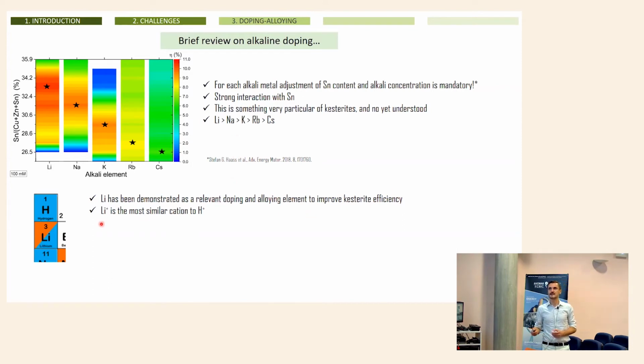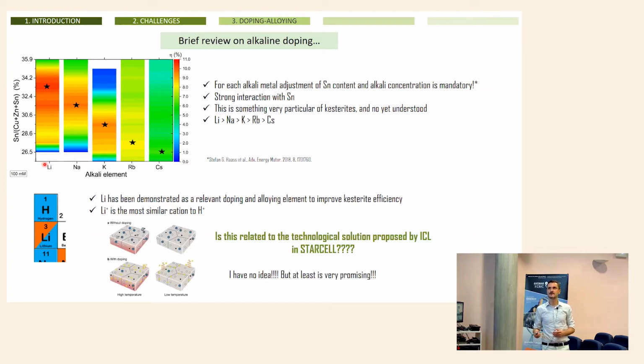But surprisingly, lithium is very similar to hydrogen. So then we started to suspect that maybe lithium is not only affecting the kesterite by forming copper vacancies and improving the conductivity. Could lithium also play a role like hydrogen to passivate all these free electrons? So we are starting to work on that, and we have evidences that this is real on kesterite, because doping with hydrogen is very complex. Doping with lithium is much easier for us.